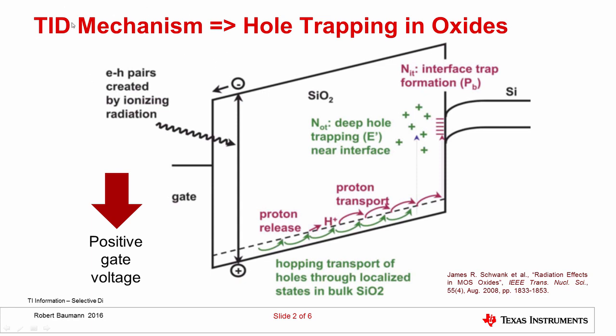The effect of radiation in the total ionizing dose mechanism is that when the gate oxide is exposed to radiation, any energy absorbed in the gate oxide produces electron-hole pairs. Basically, an electron absorbs the radiation energy, gains energy, moves up on this chart, leaving a hole behind. One feature of gate oxide which makes it problematic for total dose is that the mobility — the ease with which the carriers move in the gate oxide — is different for electrons and holes.